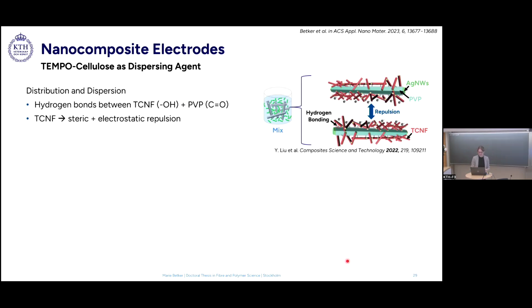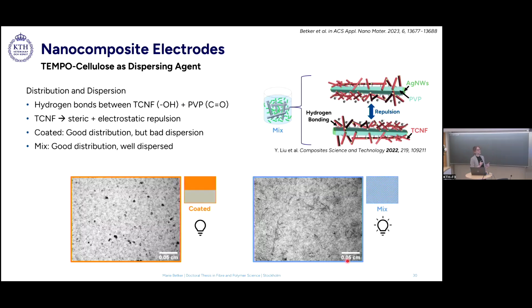And we can see this effect directly again on our two electrode types. So these are the same types we discussed already. In orange, it's the coated type, and these black lines you see are the silver nanowires. And you see in the orange case, they are well distributed over the whole sample, but the dispersion is not so good because you have these many black spots. These are actually agglomerates of silver nanowires, so many nanowires sticking together, which is bad for the conductivity. On the other hand, if you look at the mixed type in blue, we see that the nanowires are well distributed, but also well dispersed, which enhances the conductivity.